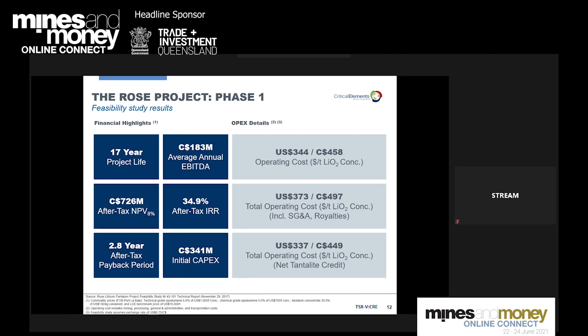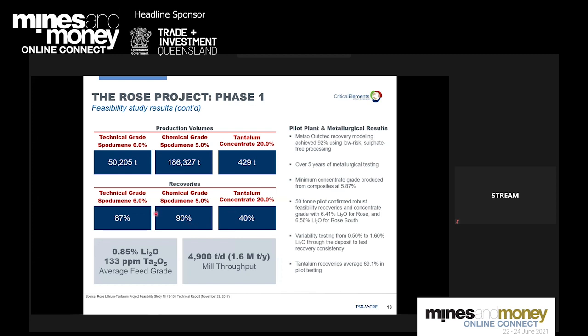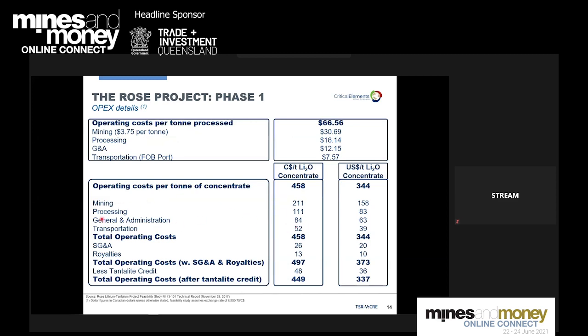Moving on, the 2017 Phase 1 feasibility study demonstrated a robust project delivering strong EBITDA over a 17-year life, and that's not limited by the deposit, but rather the amount of drilling, and a robust 35% after-tax IRR. Feasibility study results and the metallurgical studies on bulk sampling to support them show excellent recovery rates for both technical grade and chemical grade spodumene concentrate. The tantalum is a nice byproduct for the steel industry and capacitors in the electronics industry, a nice valuable byproduct for the project.